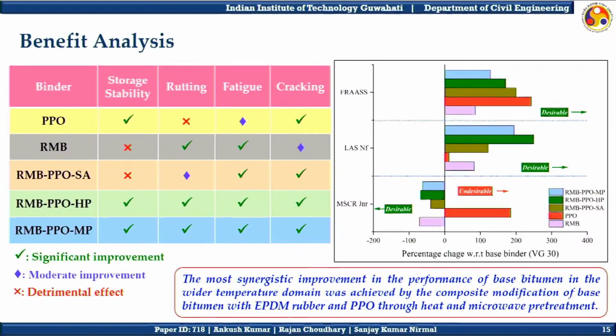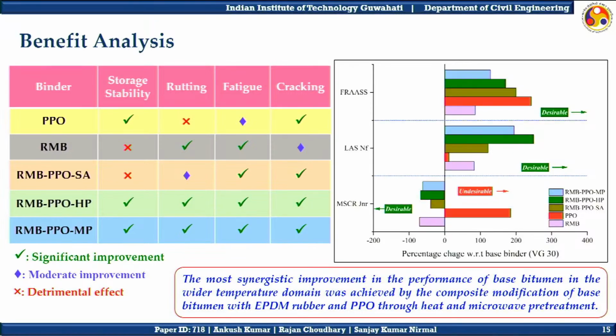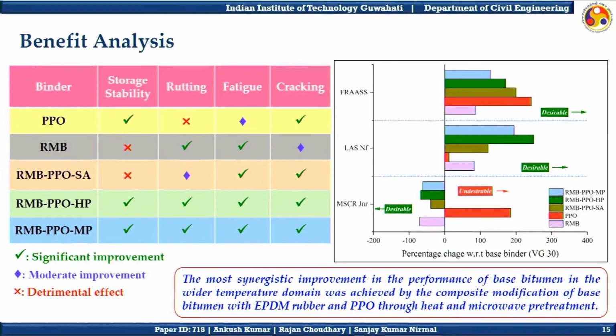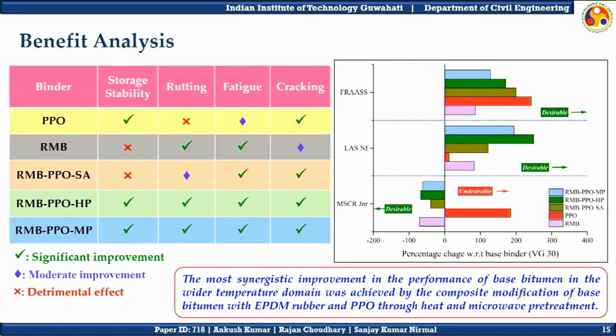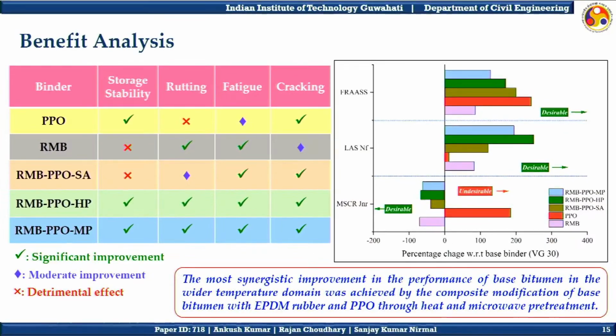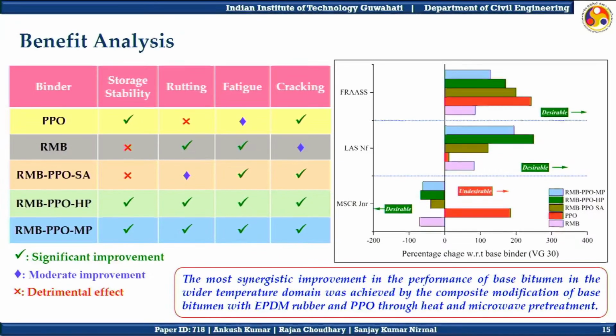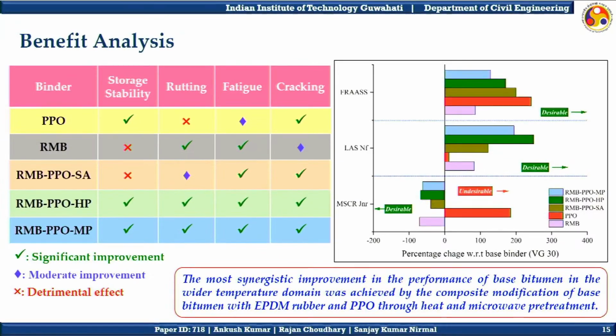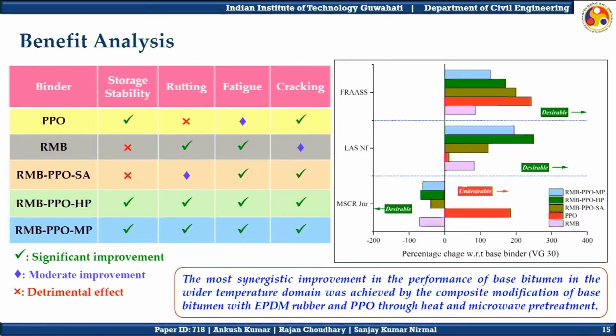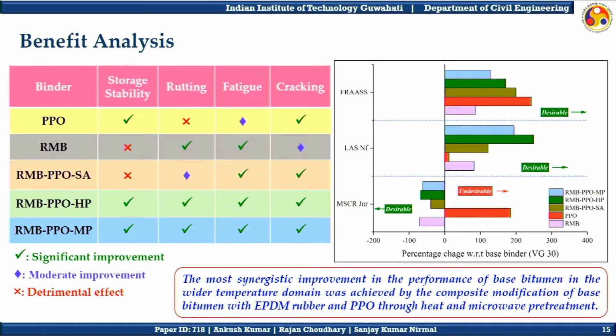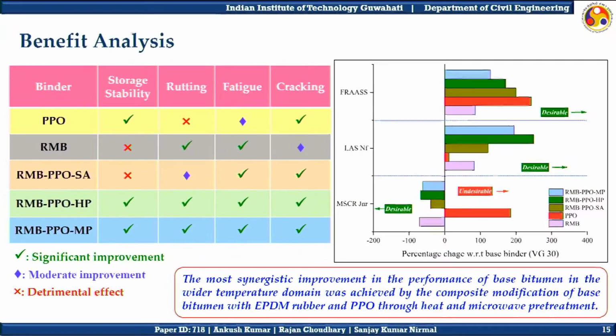That is storage stability, rutting, fatigue cracking, and thermal cracking. So the PPO binder was storage stable while it had a detrimental effect on the rutting parameter, a moderate improvement in fatigue, and significant improvement in cracking. The binder with individual modification with EPDM rubber was not storage stable, while the improvement was significant in rutting and fatigue, and moderate in cracking.